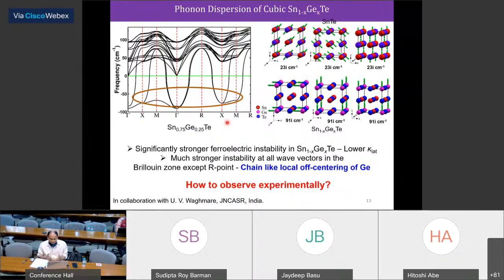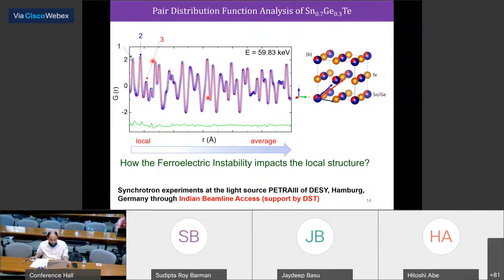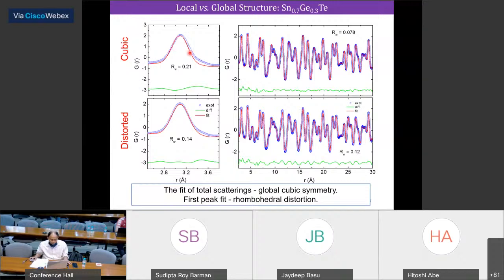So can we see this local structural distortion, which is why this ferroelectric instability is coming? In order to do that, we have done pair distribution function analysis again at Petra, and we have seen the local and global structure. The local structure cannot be fitted well with the cubic rock salt model, but the global structure is fitted well with the cubic model. But when you distort the structure along the rhombohedral direction, the 111 direction of a cube, slightly distorting the germanium, we see the local structure is fitted very well, but the global structure is not. So that means the local structure is rhombohedrally distorted because of the germanium lone pair, whereas the global structure remains like rock salt structure.